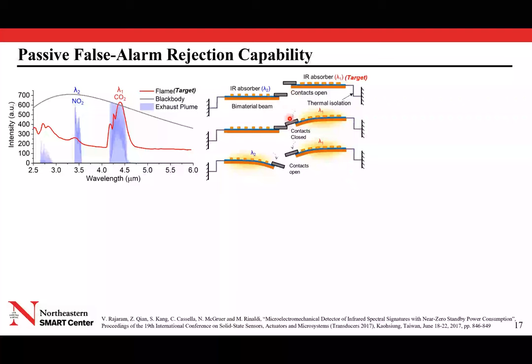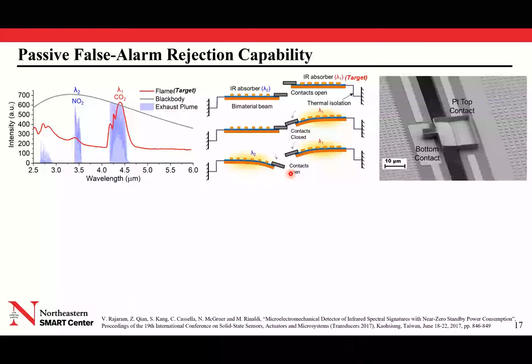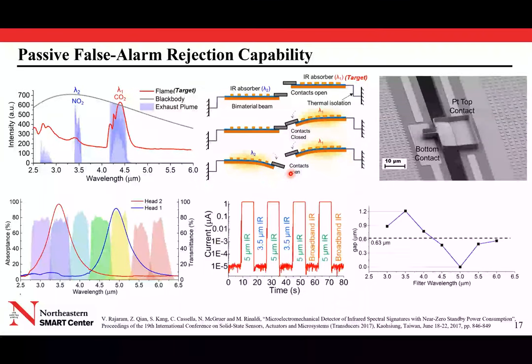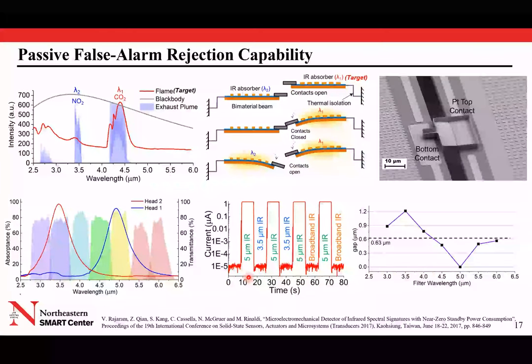And as you can see clearly, if the device is exposed only to the wavelength we want to detect, there is a relative displacement of the two heads, and therefore we can modulate that gap. But if both wavelengths are present, both cantilevers bend in the same direction, and therefore there is no change in the gap. And so we built this kind of structure, and here you see the experimental data, where you can see that the device turns on only when it's exposed to the target wavelength, and it does not turn on when it's exposed to the wavelength we want to reject or a broadband radiation that includes both wavelengths. And here you see the actual gap that separates the two contacts. You can see that it goes to zero only when the device is exposed to the target wavelength.